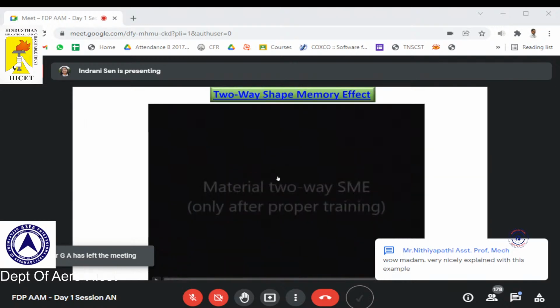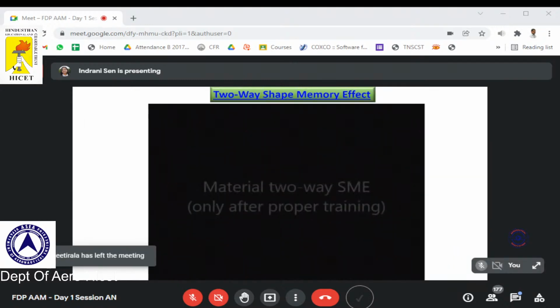Okay, now shape memory alloy is not only showing such changes in the shape, as you have seen that we are putting it in warm water and we are getting a particularly pre-designed shape. It is not only restricted to that. Rather, we can have a two-way shape memory effect, and what it means is that we can have two different shapes set in this one. In the austenite phase, when we are setting a particular shape, and then in the martensite phase we are again setting another shape, and then just by changing the temperature or by applying the stress, it can come back and forth to two different shapes. So obviously this is used for several applications where we can make use of two of the different shapes of this.